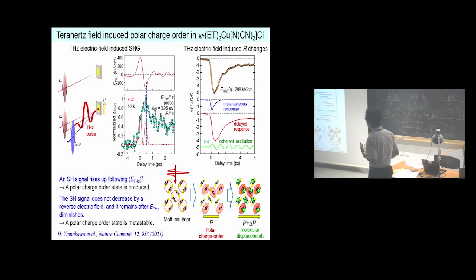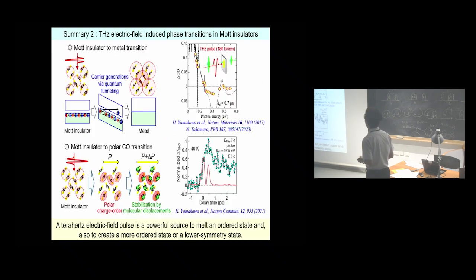The detailed analysis of the transient reflectivity changes reveals that this polar charge order state is stabilized by the molecular displacement. Let me skip the details here. Okay, this is the summary of the second part. I'd like to emphasize that a terahertz electric field pulse is a powerful source to melt an ordered state, as observed in the Mott insulator to metal transition, and also to create a more ordered state or a lower symmetry state, as observed in the Mott insulator to polar charge order transition.